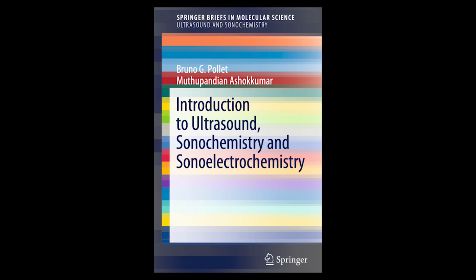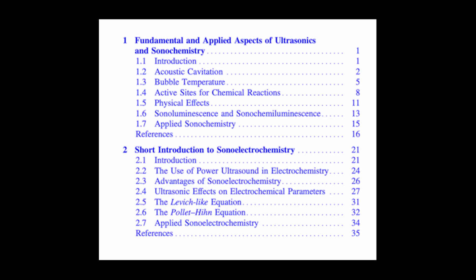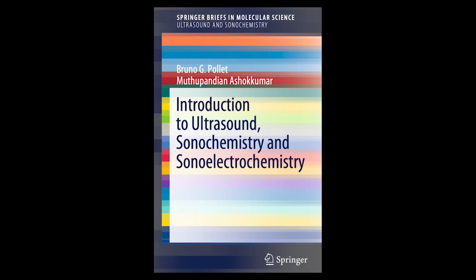But its real utility is in visualizing the cavitation activity. If you take a picture of the SCL light emitted from an ultrasonic reactor, you can see where the bubbles are collapsing most intensely, because that's where the most SCL radicals are being produced to react with the luminol. You get a map of the hot spots. What these SCL images consistently show is that the active cavitation bubbles aren't randomly scattered. They tend to concentrate in specific regions, namely at the antinodes of the standing wave pattern set up by the ultrasound reflecting within the reactor.